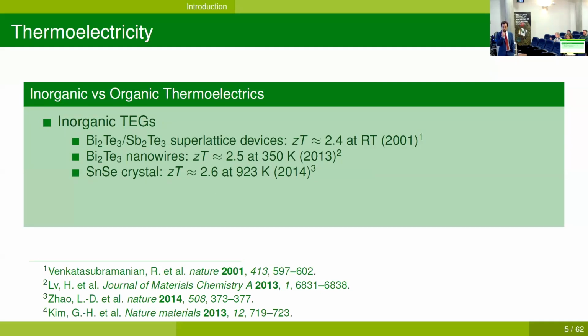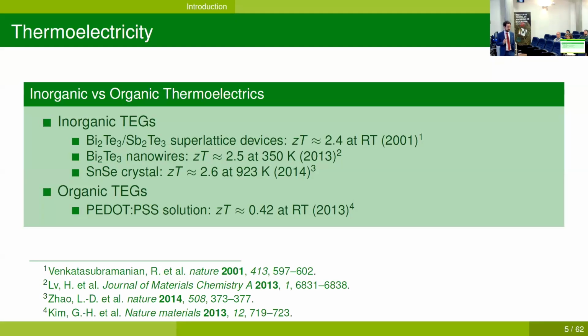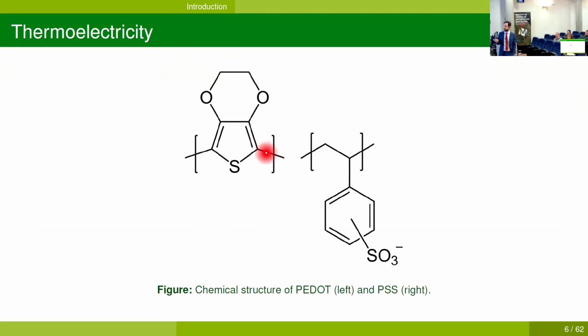When we look at the state of the art, inorganic thermoelectrics show values of ZT, the best one that we know of until now, around 2.4, 2.5, 2.6 at various operational temperatures, and they are made of elements such as bismuth, telluride, antimony, tin, and selenide. Whereas organic thermoelectrics usually employ organic semiconductors, and one of the best we know of is PEDOT:PSS in solution, which shows a significantly lower ZT at the moment of 0.42. Just to show you the chemical structures of PEDOT and PSS.